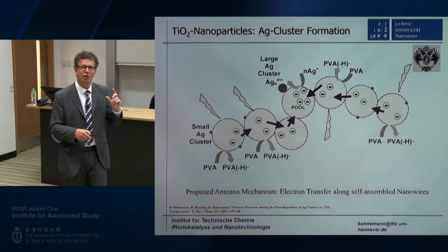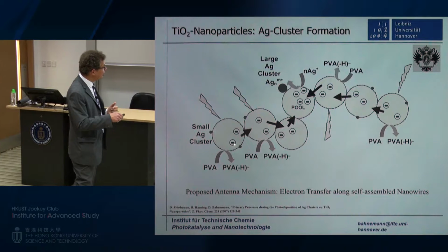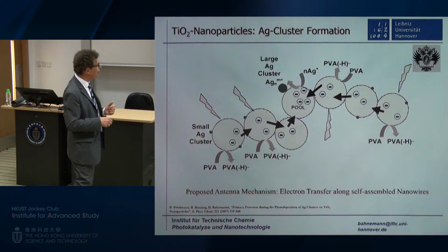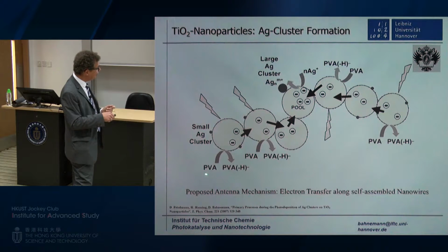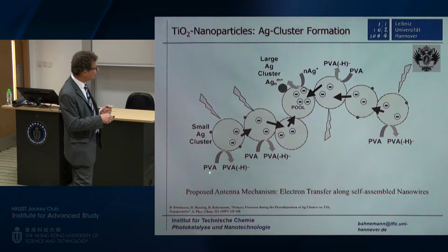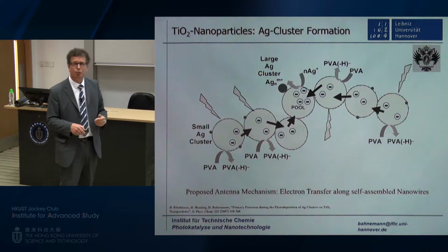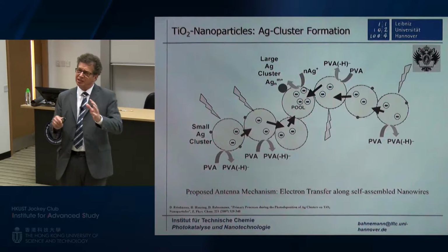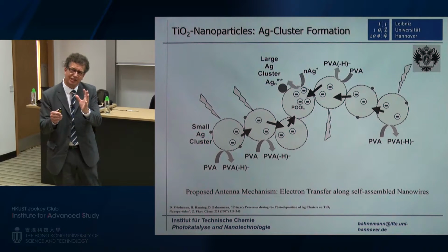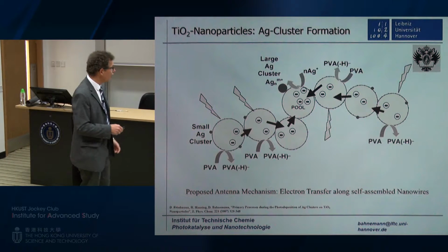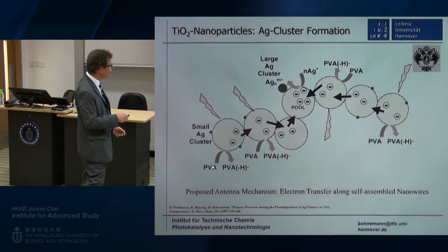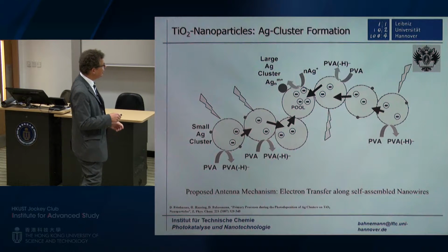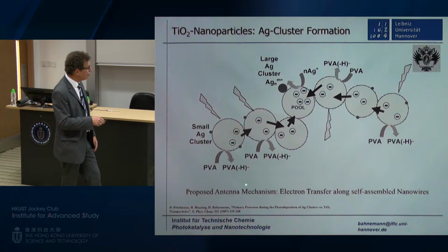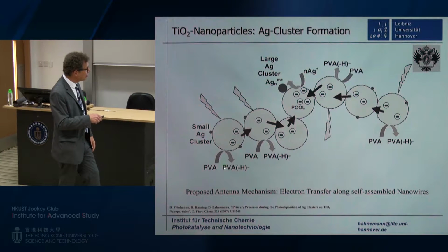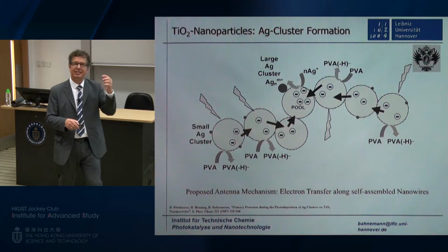What happened to the hole? The hole was, in this case, converted into a second electron by having an alcohol present. This alcohol, in this case, it was polyvinyl alcohol, which at the same time also acted as a stabilizer of the system. This alcohol is a very good electron donor. It donates an electron, fills up the hole, forms an alpha hydroxy alkyl radical in the first place, and this